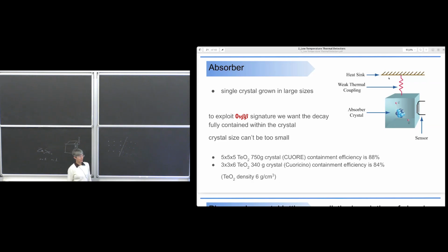because of course there is still behavior that we do not completely understand, but we have never been able to correlate crystal performances with radio purity, unless you see a crystal that is highly radioactive. But at the radio purity levels that we are using in CUORE or CUPID, they do not provide any contribution to the heat capacity, at least for what we know. And additionally, the radio purity of the tellurium dioxide crystals that we purchased in China was already very good when we started.